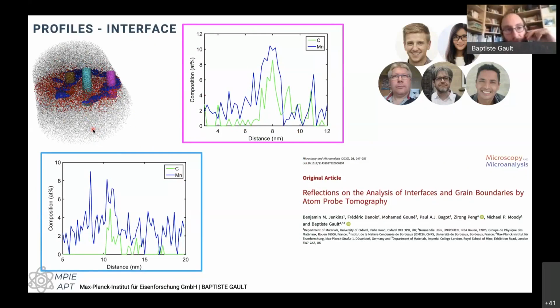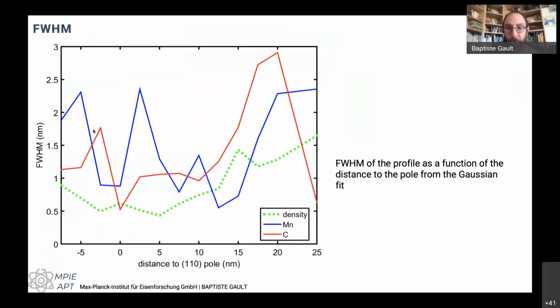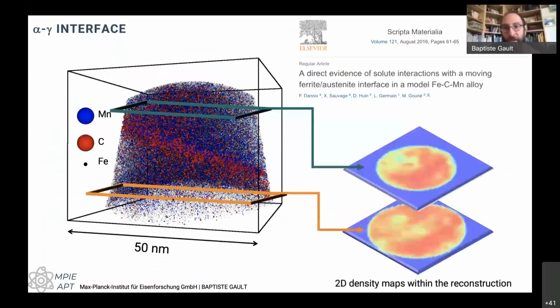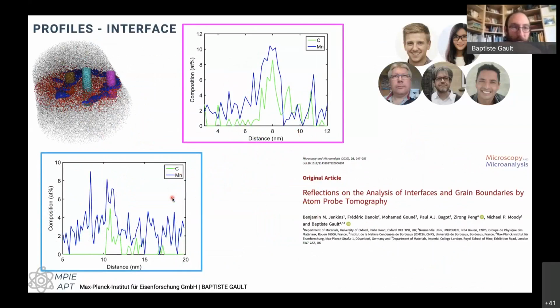So it's quite an interesting case for me because the guys in France actually published that paper, and then I looked at their data again and I showed them that they were wrong, which was quite fun. I mean, they're friends, so they didn't mind. But I think it's really an interesting case of data that was not interpreted properly. And if we start scratching the surface, there's a lot more that we can say about it. So it's one of these things where we could show that if we prepare the samples in the right orientation to maximize the resolution of the analysis, then we'll probably get results that are more meaningful and more interesting from a material standpoint.